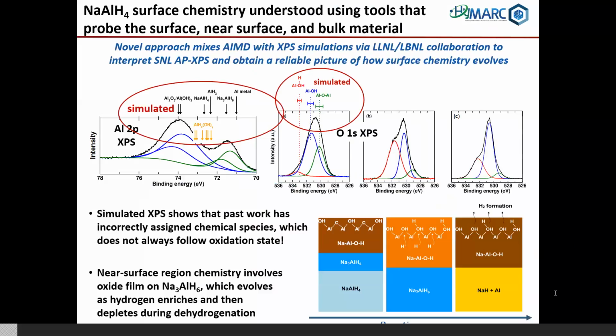One is that titanium, whatever its role is in the desorption, it's not occurring on the surface. We don't see any titanium species on the surface of this material during the process of desorption. And we were able to probe that several ways, the low energy ion scattering, but also ambient pressure XPS experiments at the ALS. But the other thing that we learned, which really came as a surprise to us, is that there are oxygenated species on the surface of this material that appear to accelerate the desorption of hydrogen. They are, in fact, essential to the behavior of the material.